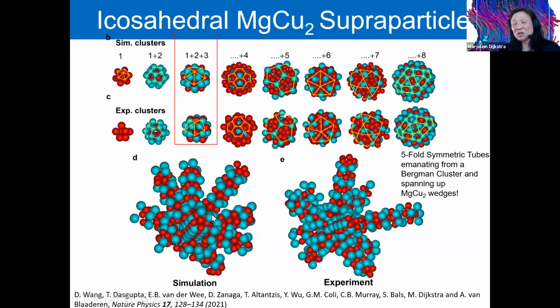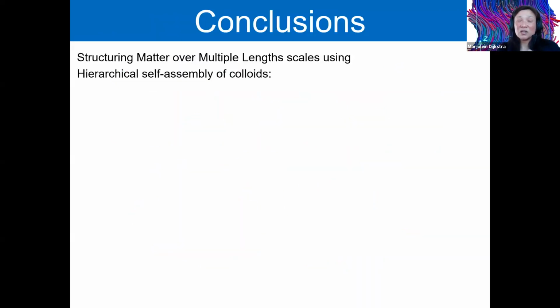So just putting big spheres and small spheres in a big sphere, it self-assembles spontaneously, purely entropy driven, into this very beautiful structure where it really forms all these layers of icosahedral, dodecahedral, etc. layers around a central sphere. And then with all these pentagonal tubes, 12 of them, that basically spans up all these magnesium copper 2 wedges. So I find this really awesome that it really self-assembles this way, both in experiments and in simulations.